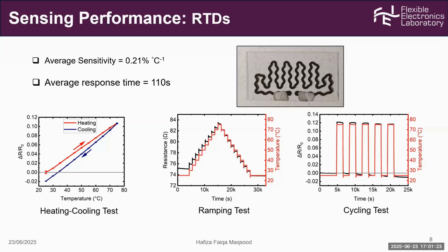And then we performed the cyclic test, where the temperature was increased and then reversed. The sensor shows very stable and reliable performance under all of these tests, and the calculated average response time of the sensor is 110 seconds. That is quite reasonable for this type of passive device and this type of polymeric substrate.